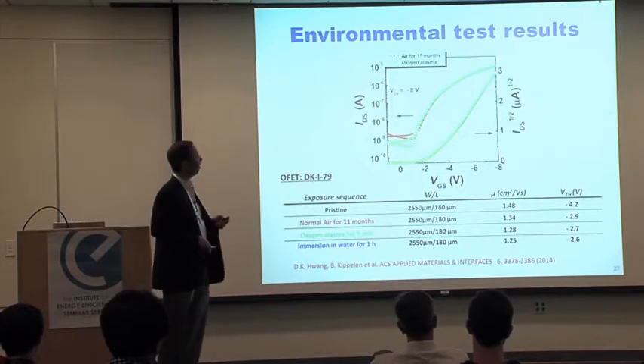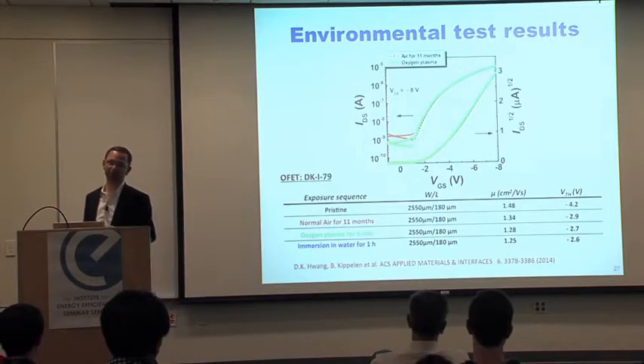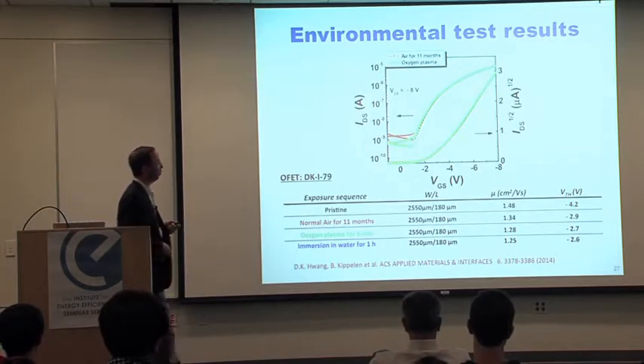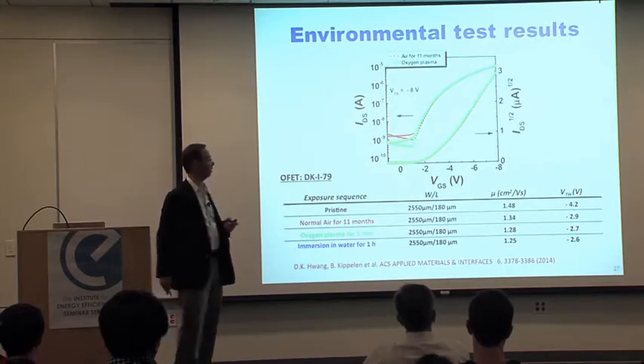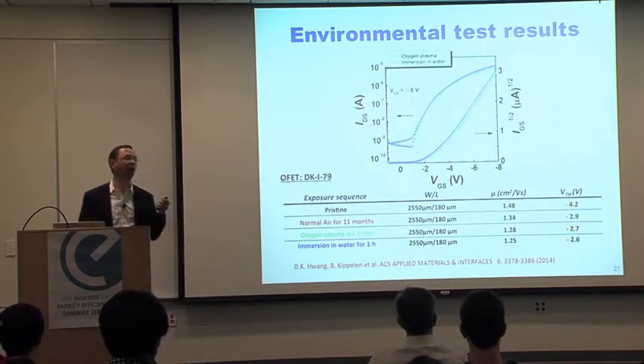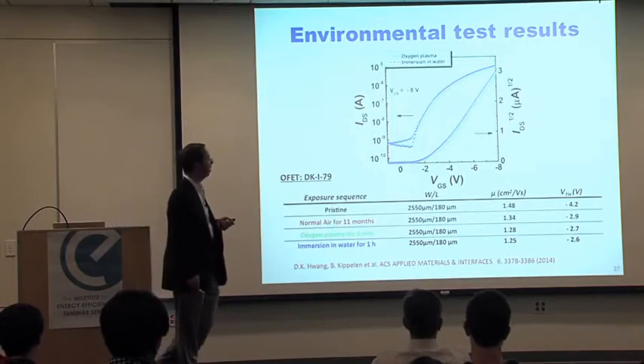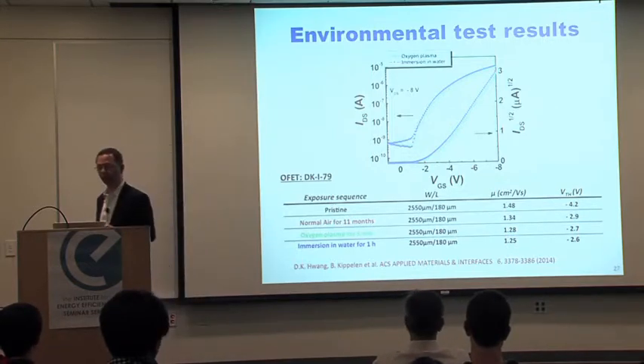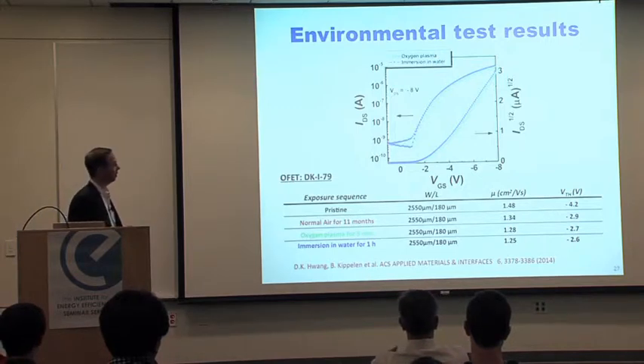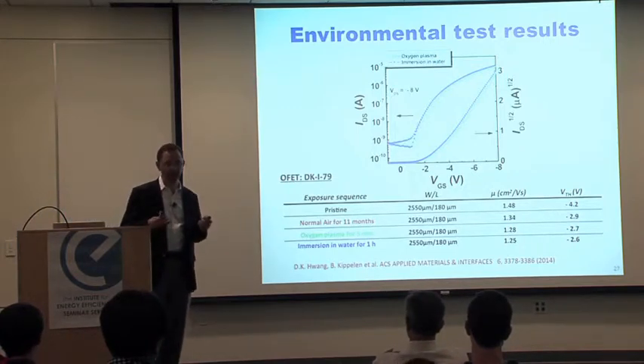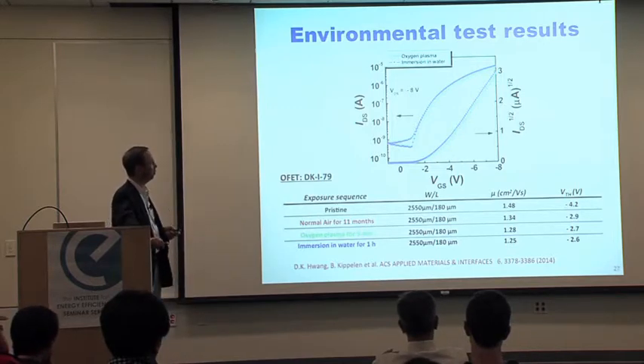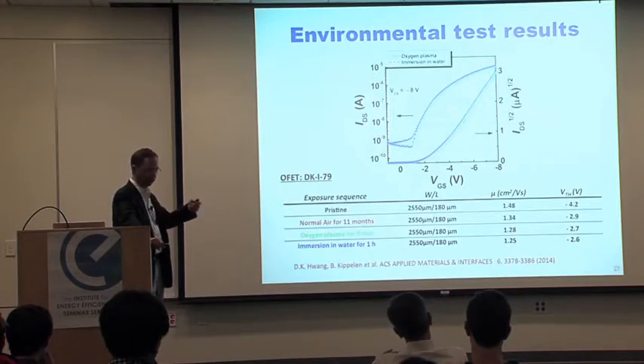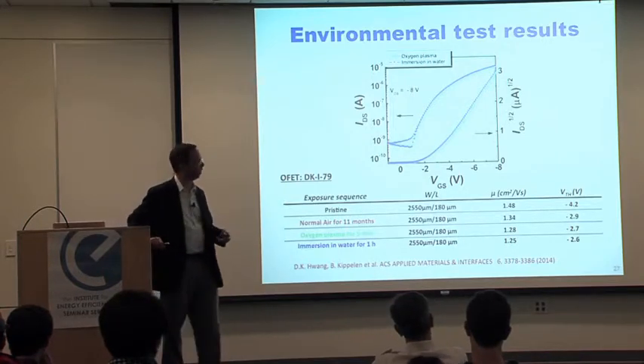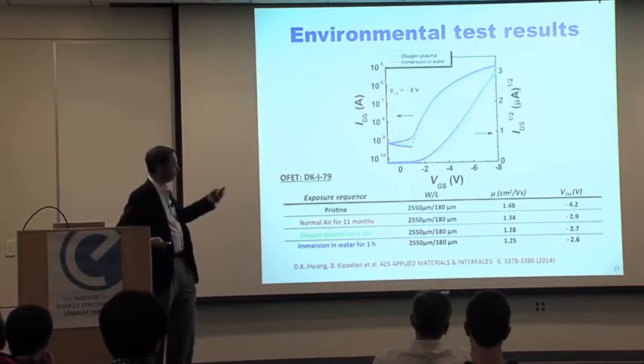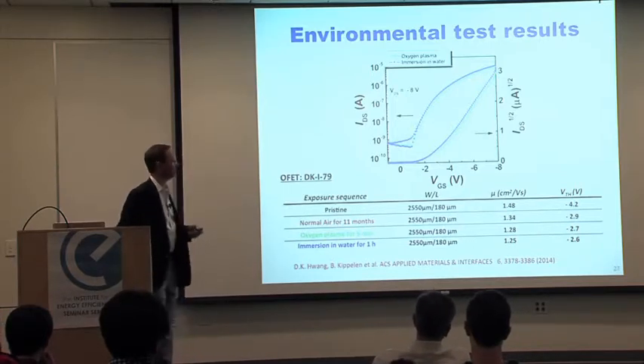But here is before and after the 5 minutes in the plasma chamber. So, not only do these transistors still work, but you can see there is very little change in the transfer characteristic. This is before and after 1 hour immersion in water. Again, very little change. And so just to illustrate that organic semiconductors can be made very stable if you incorporate them in the right device architecture. And of course, that particular bilayer gate dielectric is also a good barrier. It protects the semiconductor from the environment, so it works quite well.